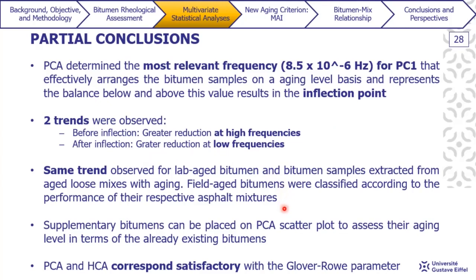And we also got the same trend observed for laboratory aged bitumen recovered from loose mix aged in the laboratory, and also bitumen samples extracted from the field, which in this case were classified according to what we knew already beforehand, the performance of their respective asphalt mixes. In this case, supplementary bitumen can also be placed on the PCA scatter plot just to assess their age level in terms of the already existing bitumen. We could add more individuals, not interfering in the process, but just adding the individuals to see where they would be placed according to what we have to date. And PCA and HCA correspond satisfactorily with the Glover-Rowe parameter.